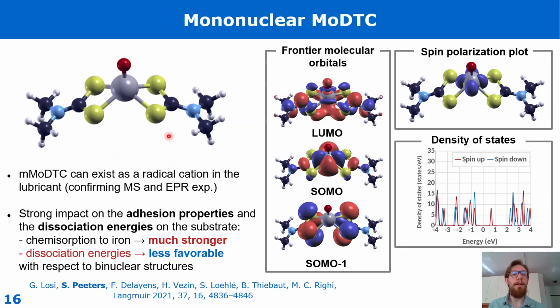All the ligand units surrounding the molybdenum atom account in total for 4 bonds, so 1 for the left unit, 1 for the right unit, and 2 for the double bond with oxygen. But EPR revealed that the oxidation number of molybdenum is +5, and the only way to combine the results from mass spectra and EPR is to consider mononuclear MoDTC as a radical cation.